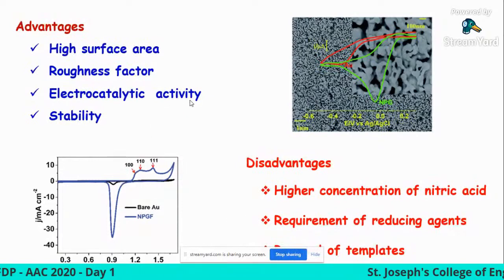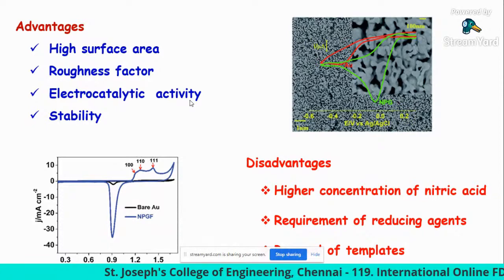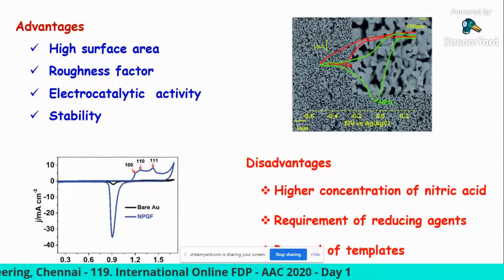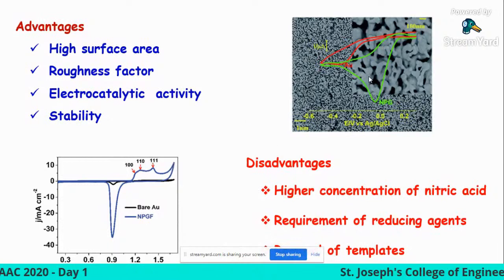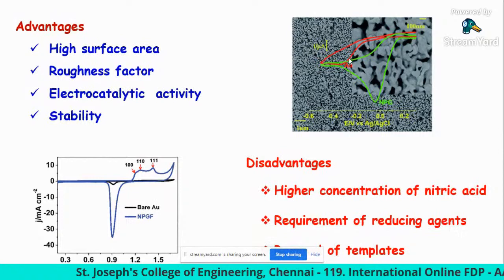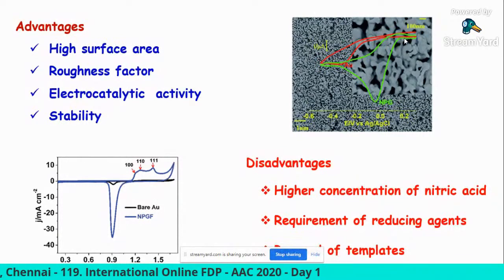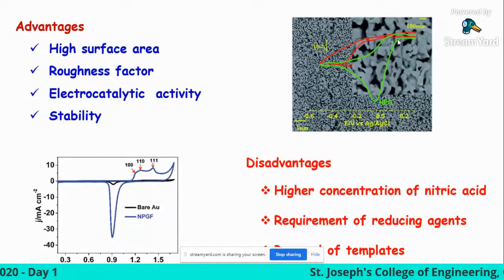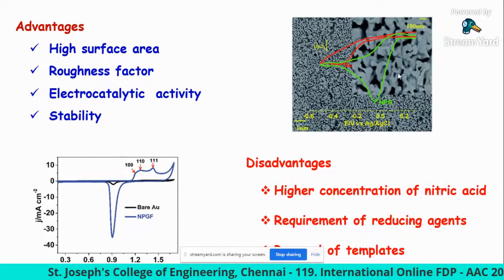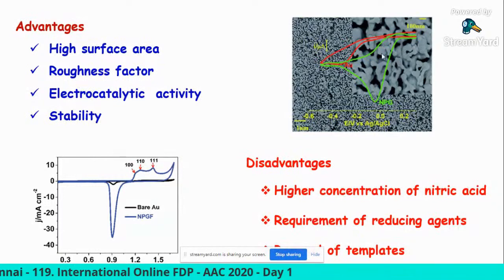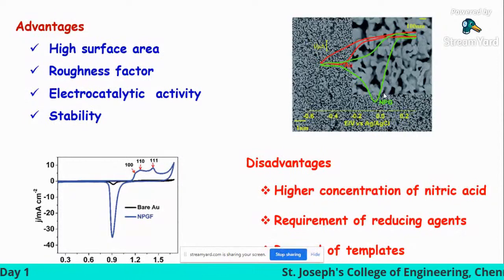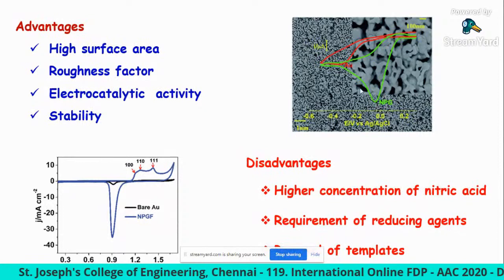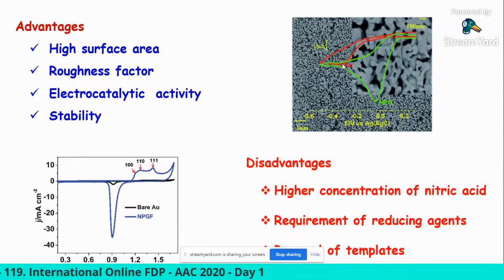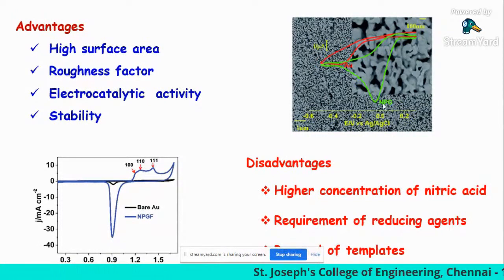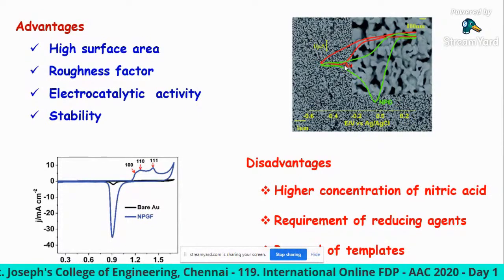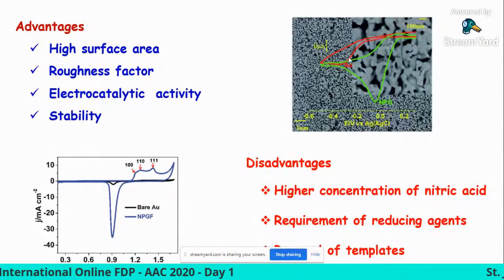So what is electrocatalytic activity? If your material shows a very good electrocatalytic activity, it has two properties. This is an example to explain the electrocatalytic activity to understand it much better. This is the cyclic voltammogram recorded for the oxygen reduction reaction for bare gold, the red color, and this is the nanoporous gold in green color, where you can see this is called the onset potential. Where the current is raised, this is called the onset potential. The onset potential for bare gold compared to nanoporous gold shifted around 300 millivolt towards the less negative direction. Also, see the peak potential for bare gold, the oxygen reduction reaction takes place at around minus 0.3 volt, whereas for nanoporous gold, it shows close to 0. So the potential is shifted towards the less negative direction, as well as the current is increasing.